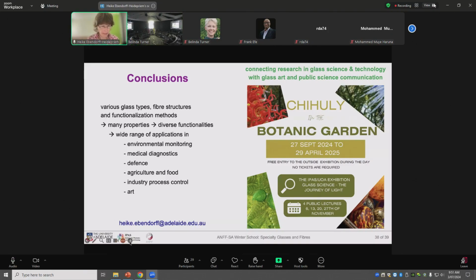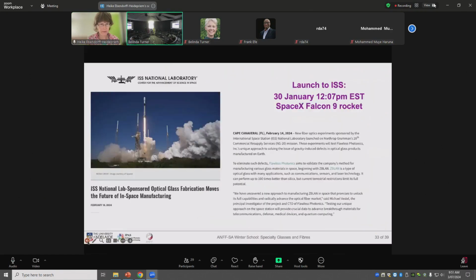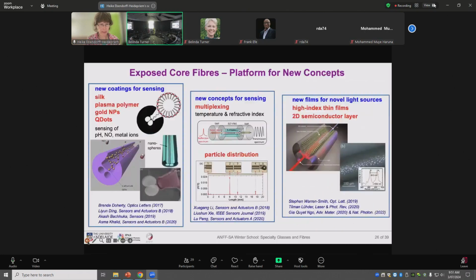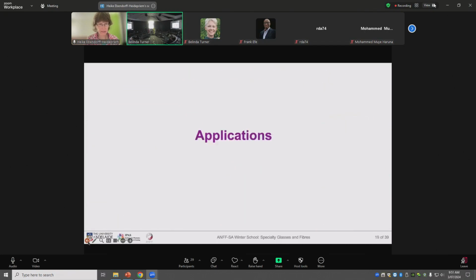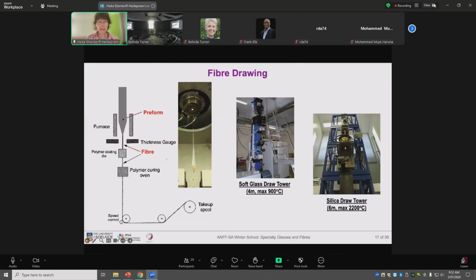So let me go quickly back. Yeah, any moment there, because it's then easier to explain. So the preform, a short section of the long preform is heated up. The glass deforms. And therefore, if now a tension is put at this fiber, so first, here on Earth we are so lazy, so easy, gravity makes the drop come down. We remove the drop, and then the dangling fiber is put onto the drum, which then starts to rotate. So the preform goes slowly into the hot zone, via drum rotation fast out of the hot zone, and therefore from millimeter scale the glass is stretched down to the micrometer scale.